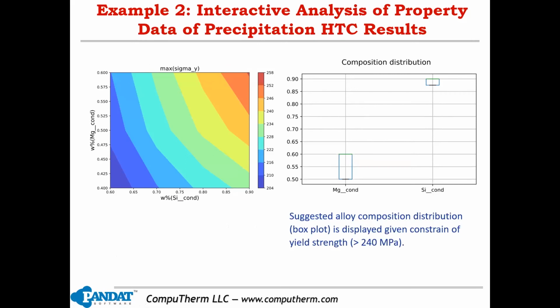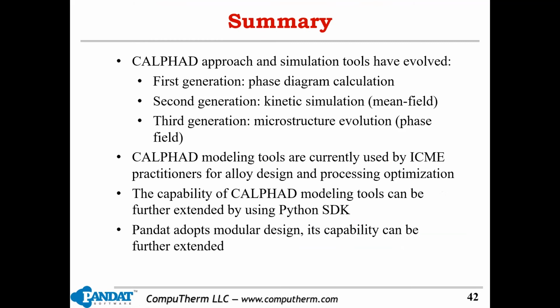And in this example, it basically analyzes the data from high throughput calculation of a precipitation simulation. And the left figure shows the maximum yield strength varying with the composition of silicon content and magnesium content. And then the right figure shows you the composition range for magnesium and silicon where you can reach a yield strength higher than 240 megapascals, okay? So this kind of analysis is very helpful to see immediately how you can optimize your composition, okay? All right, this is my last slide.